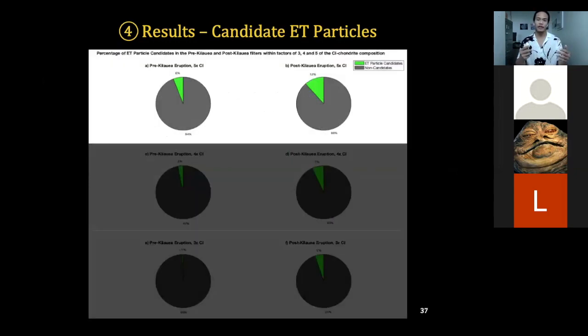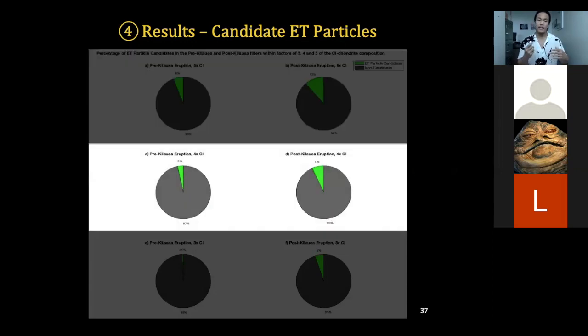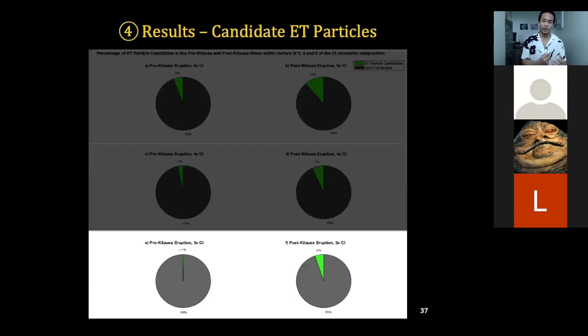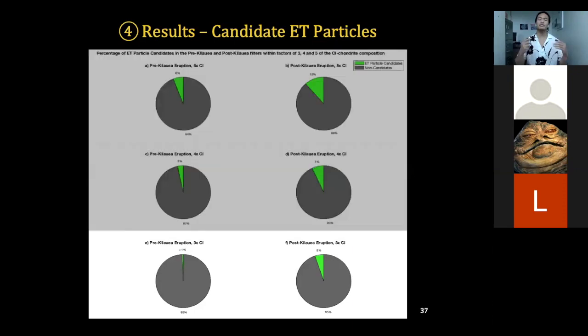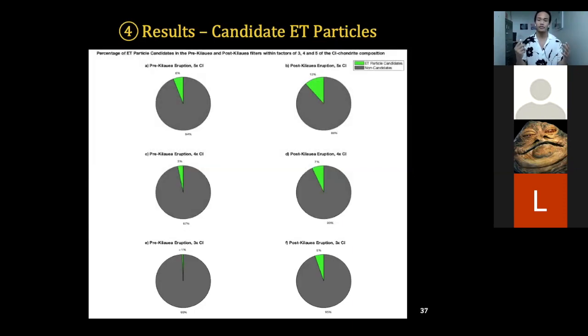Highlighted right now is the factor of 5 for pre-Kilauea and post-Kilauea, with 6% and 12%. For a factor of 4, now there's 3% for pre-Kilauea and 7% for post-Kilauea. And for an even stricter factor of 3 times the CI chondrite composition, there's less than 1% for pre-Kilauea and approximately 5% for post-Kilauea. As you can see, the stricter the factor is, the fewer extraterrestrial particle candidates there are, which makes sense. But again, we used the higher factor of 5 to not exclude particles due to uncertainties in our measurements caused by a physical overlap of grains.